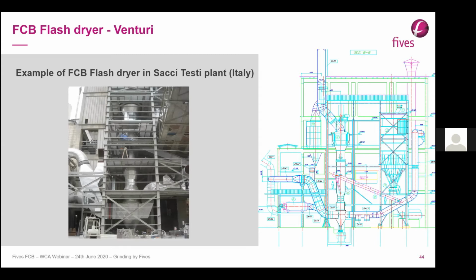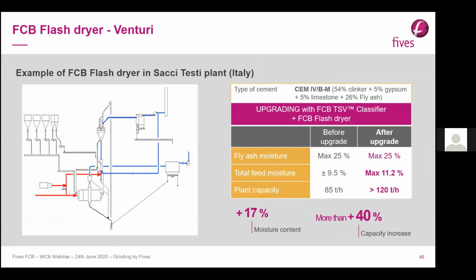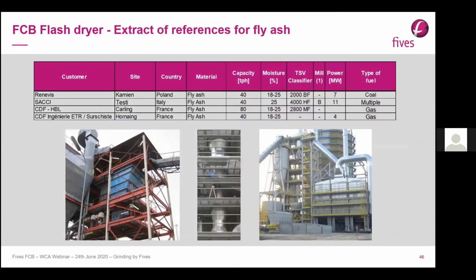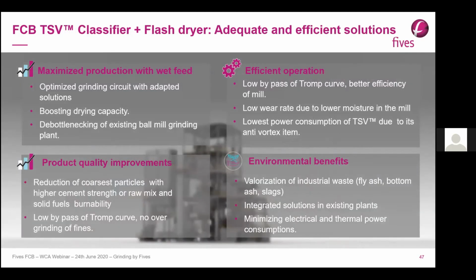After the installation of this flash venturi and TSV, we achieved the following process result with more than 40% capacity increase, from 85 up to 120 tons per hour. This is a short list of flash dryer applications for fly ash. And the last slide is a summary of what I said before.